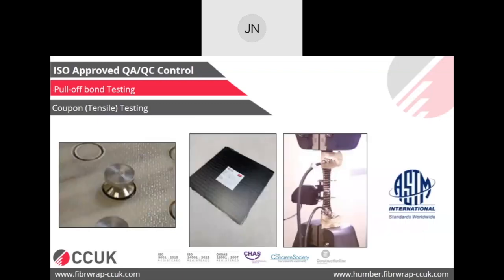And then the second test is basically to check the material properties, that whatever material you have designed your system based on is actually used on that project. So the requirement as per TR55 is to cast these 12-inch by 12-inch plates or sample plates. And currently the requirement states that you need to cast 2 plates per roll of fibers or 2 plates per day if it is less than a roll job. You send it to an independent laboratory, they'll cut a coupon out of them like this and do a tensile test. And those tensile properties should match with the data sheet. And that's the pass criteria for this test.